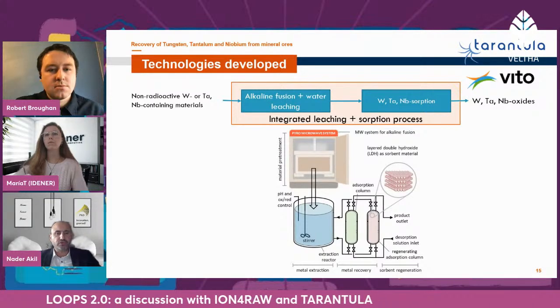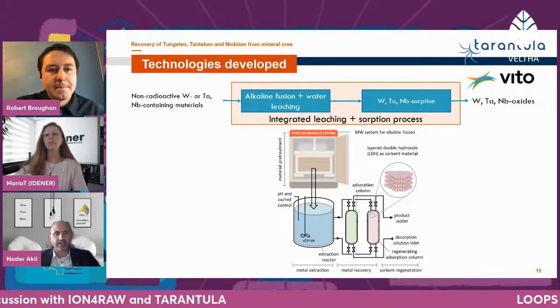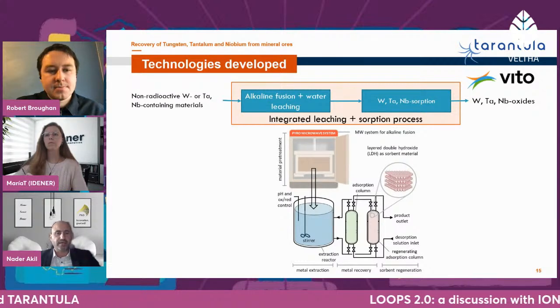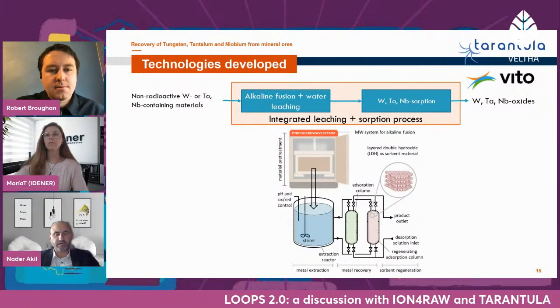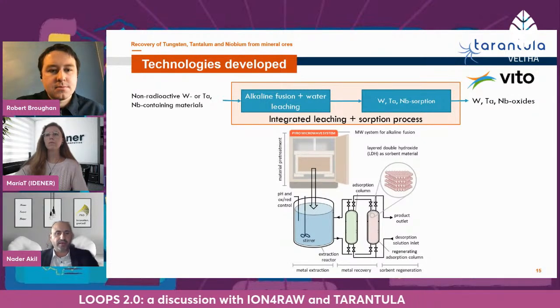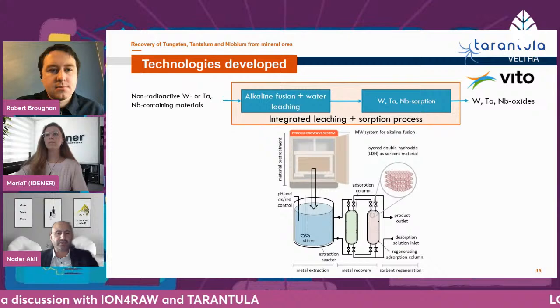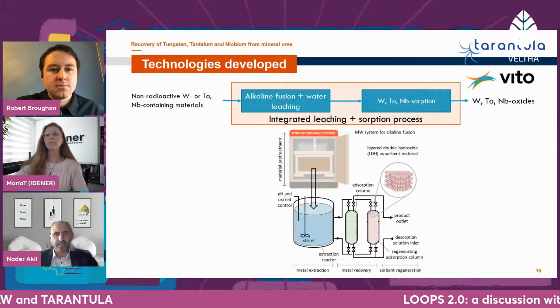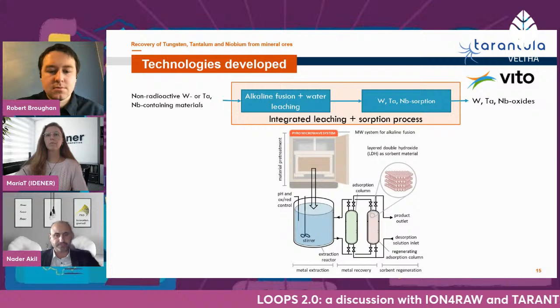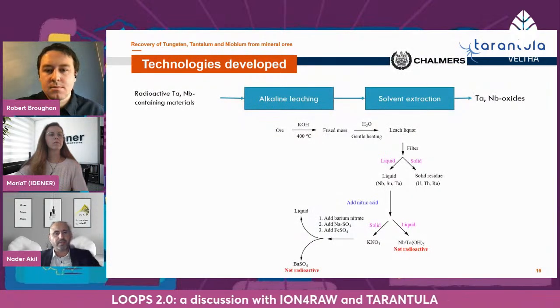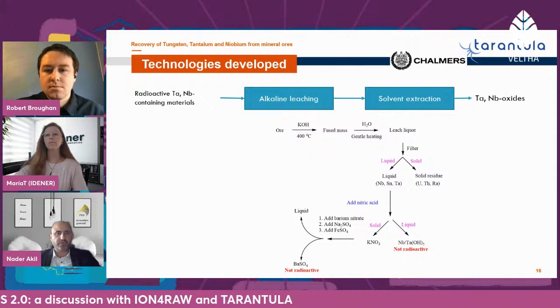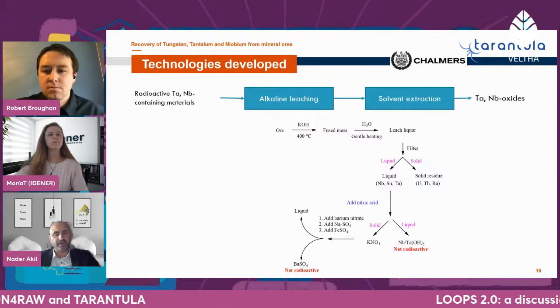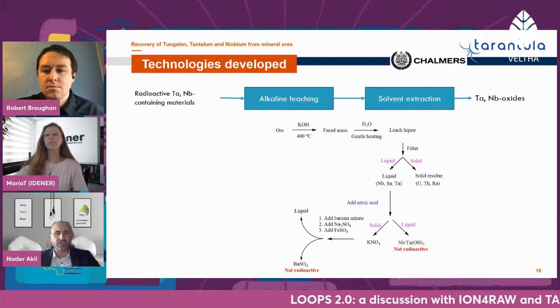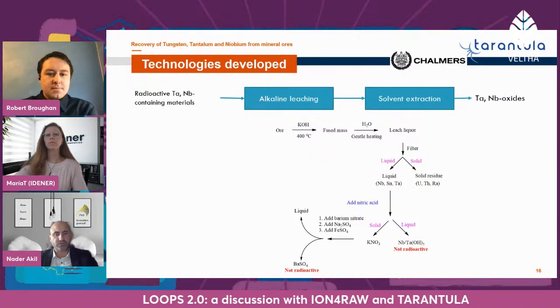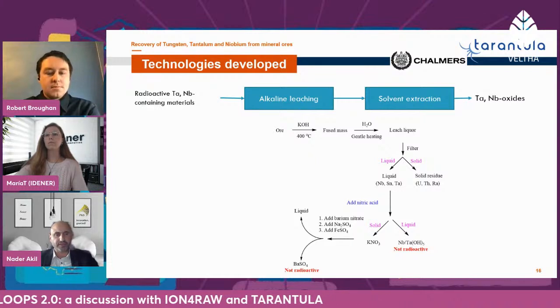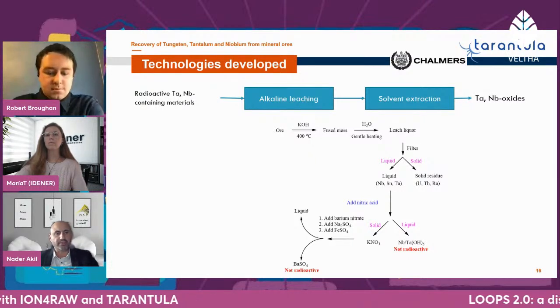The process of Vito is based on alkaline fusion and water leaching, followed by sorption. The importance of this process is that it is integrated in one processing step to produce the metal oxides. And with Chalmers, as said before, we are using a specific process, alkaline leaching and solvent extraction, in order to remove any hazardous material from radioactive tantalum and niobium containing materials.